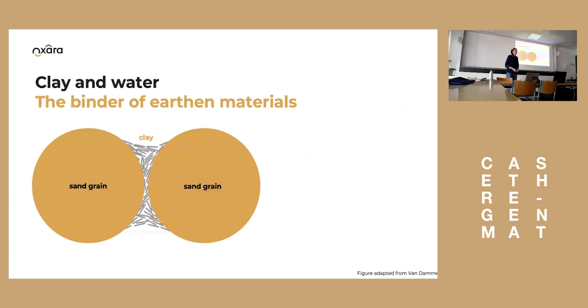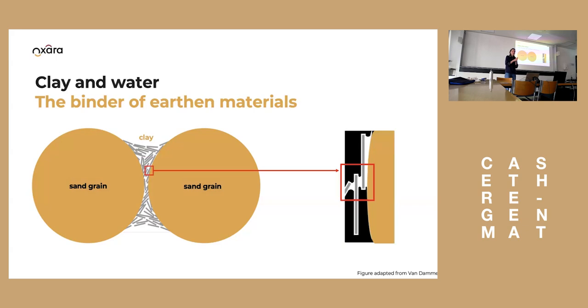And to understand the earthen materials, I think it's very helpful to have this picture in mind, that in your earthen materials, you have the different grain sizes. And then you can imagine that you have the sand grains, and around these sand grains, you have the clay platelets that are oriented as the matrix around. And then if you zoom in even to these clay platelets, you find in between the clay platelets the water that is in the very small pores as capillary bridges. And it's actually these capillary bridges that give the cohesion of the clay-based building materials. And it is also this